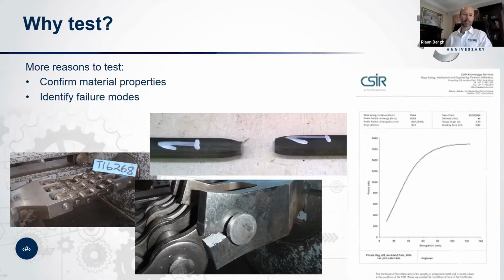So just by way of quick background, the photographs you see in the bottom there is a sample of a large size triplex drive chain. To give you an idea, the width of the chain, as you see it in the picture there, is just over 0.5 meter. And the customer required a proof load test to confirm the integrity of the chain, but he also needed to confirm that the ultimate strength was above a certain minimum threshold.